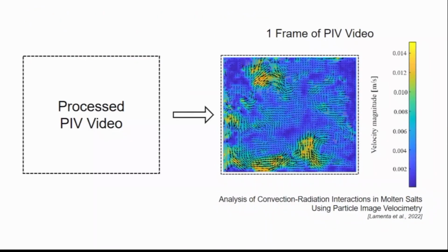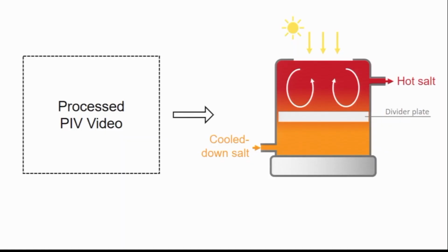So looking at one frame of this PIV and everything that's going on in the lab, it's maybe not clear how all of this ties back to a system containing thousands of kilograms of salt. Well, from my PIV experiment, I'm able to obtain a lot of fundamental data on the molten salt. I can gain information on the velocity fields, on the formation of convection cells, on the onset of turbulence, and even on the intensity of that turbulence. And this is all data that goes a long way in helping our understanding of natural convection and how it behaves with thermal radiation. And this is essentially exactly the passive mixing that's going on in our large-scale system.